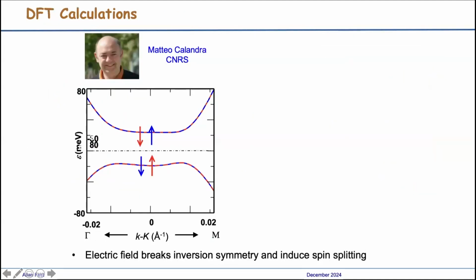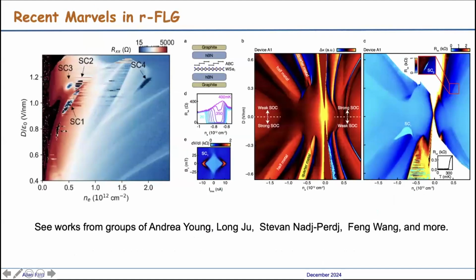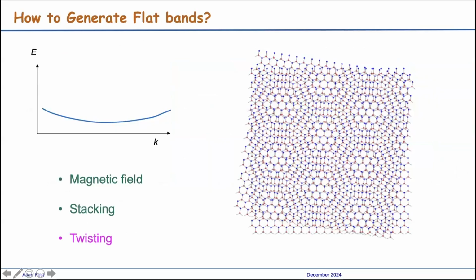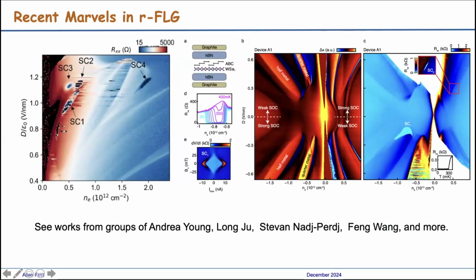Okay, we collaborated with Matteo Calandra's group, which shows that the electric field breaks inversion symmetry and induces spin splitting. Let me just be roughly brief. Of course, we know the recent marvelous works on rhombohedral few-layer graphene. So we would also like to return to this system, but probably with a slightly new twist, meaning that we want to put this on a slightly different substrate. That brings me to the next topic of my talk, a substrate with more screening. I want to see what happens to all these phases.